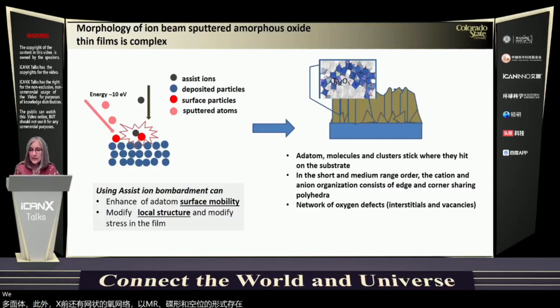We can, to a certain extent, modify the structure because in our system, we have an assist source that is directed towards the growing film. So we sometimes use it specifically to modify microstructure and reduce stress, by bombarding the film during growth.